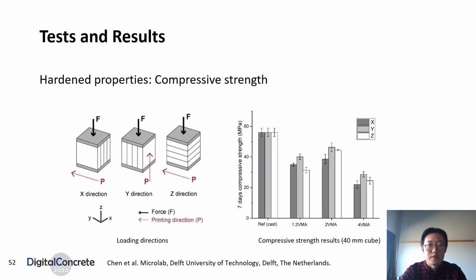The 7-day compressive strength is tested on the printed samples at 3 different loading directions. Generally, increasing VMA dosage leads to the decrease of compressive strength, but mixture 2 VMA shows slightly higher strength than 1.2 VMA. The strength of hardened cementitious materials is mainly influenced by the content of air voids and capillary pores.